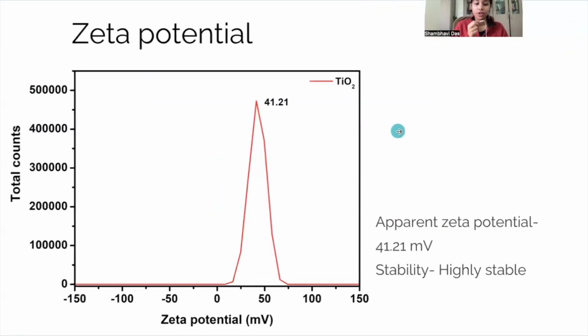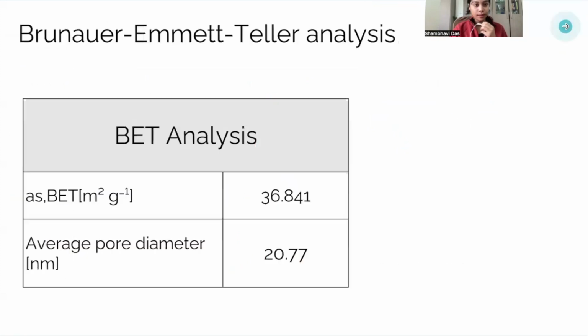Coming to the zeta potential. The zeta potential graph, as we can see, is very pointed and tall. This tells us that the charge is uniform in the sample. And as we can see that the zeta potential is about 41.21 millivolts. This tells us that the sample is highly stable and also positively charged.